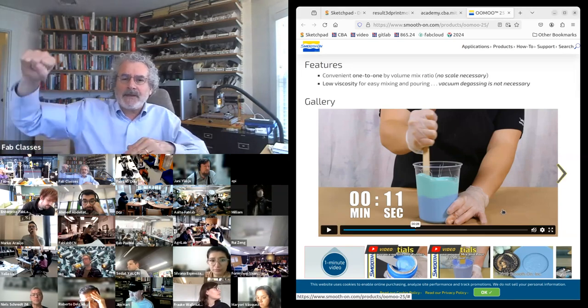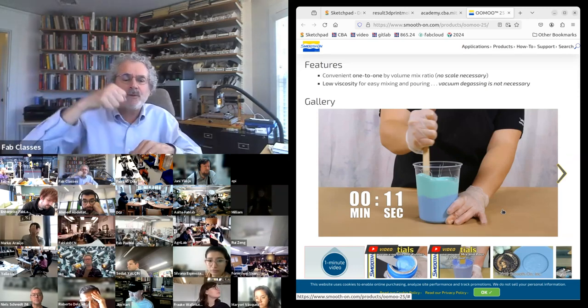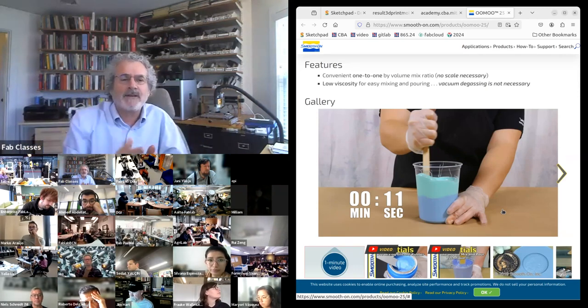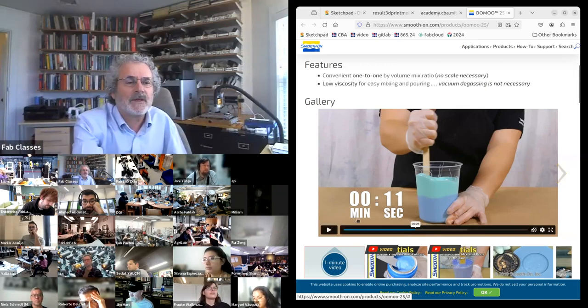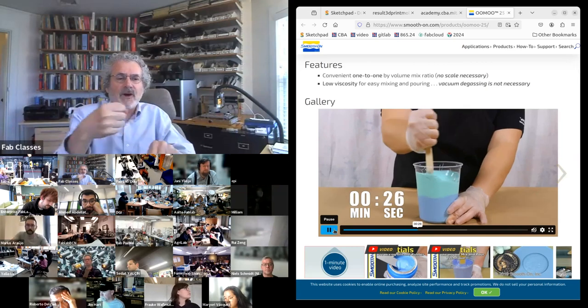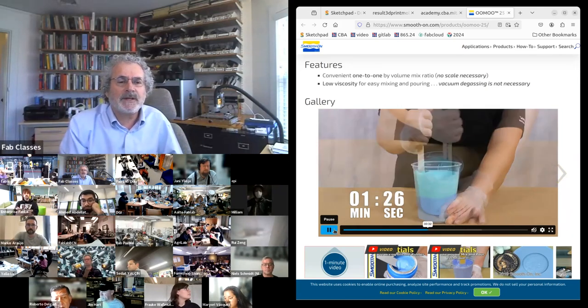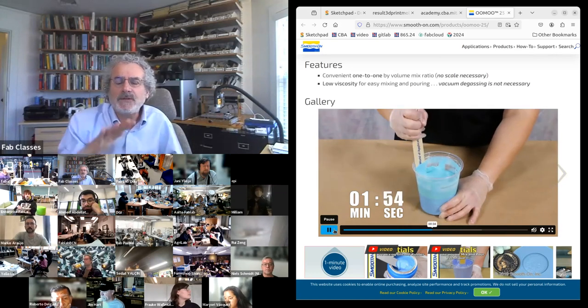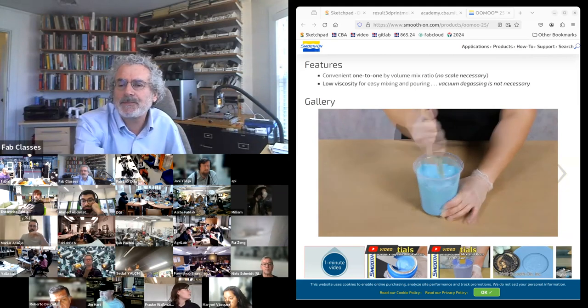Right now, if you scoop like you naturally will do when you're mixing, you're driving in air. The mixing here is done by shearing. So it's shearing horizontally and then scooping around the edges to get material trapped there. And you keep doing it until it's homogeneous, until there's no color.